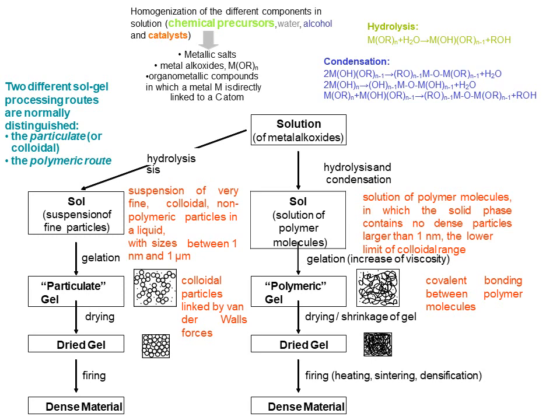At the left side, we look at a suspension of very fine colloidal non-polymeric particles in liquid with size between 1 nanometer and 1 micrometer. Then the gelation process occurs, a particulate gel is formed, then drying occurs, a dried gel is formed, then firing, and a dense material results. If we look at the right hand process, then hydrolysis.